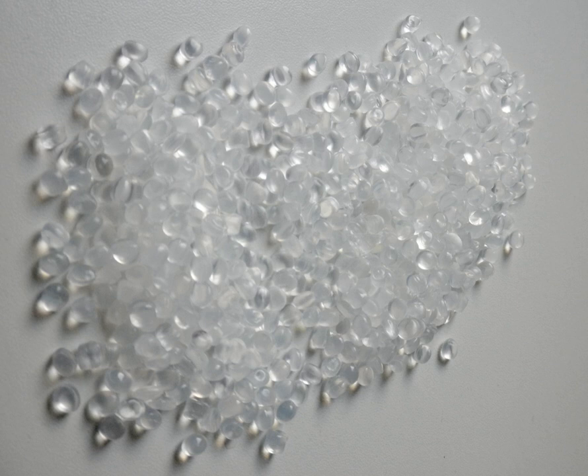The crystallinity is between 35% for PE-LD and PE-LLD, and 80% for PE-HD. Within crystallites, polyethylene has a density of 1.0 g/cm^3, in the amorphous regions of 0.86 g/cm^3. Thus, an almost linear relationship exists between density and crystallinity. The degree of branching of the different types of polyethylene can be schematically represented as follows. The figure shows polyethylene backbones, short chain branches and long chain branches. The polymer chains are represented linearly.